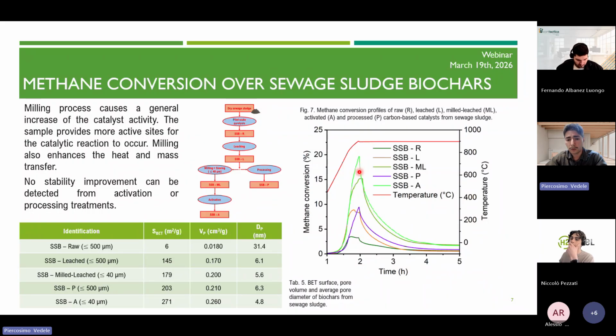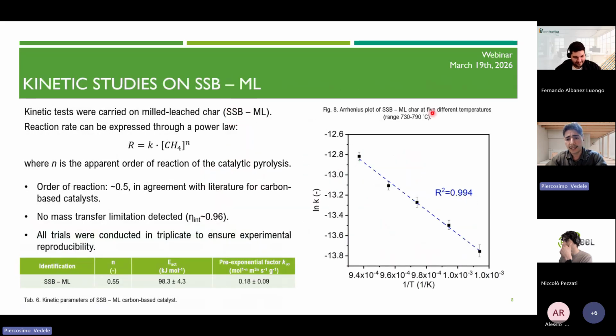The activation allows us to reach a slightly higher conversion, and for this reason, we decided to proceed with our further kinetic and activation tests with the milled-leached char, because it represents the best compromise in terms of environmental impact of the upgrading and of course, the cost of the upgrading itself. The kinetic tests were conducted at several temperatures, and at each temperature we changed the methane concentration, and we were able to model the reaction rate through a really simple power law.